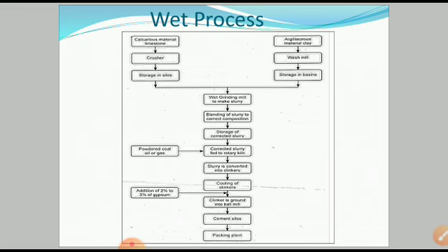The slurry is pumped to slurry tanks or basins where it is kept in an agitated condition by means of rotating arms with chains or blowing compressed air from the bottom to prevent the settling of limestone and clay particles. The composition of slurry is tested to give the required chemical composition and corrected periodically in the tube mill and also in the slurry tank by blending slurry from different storage tanks.